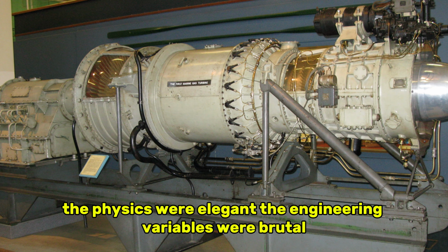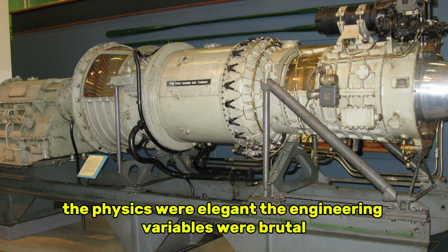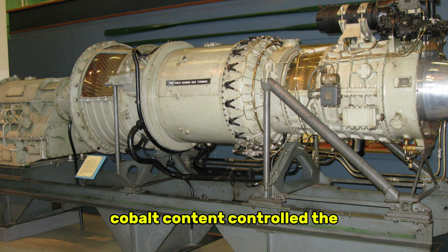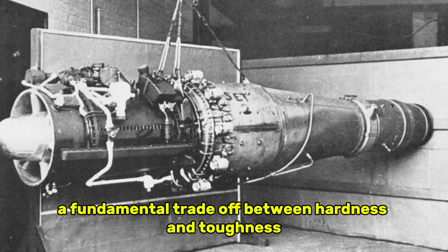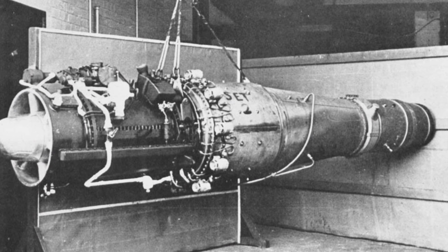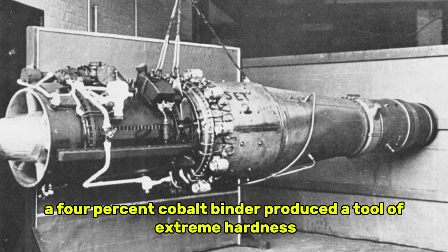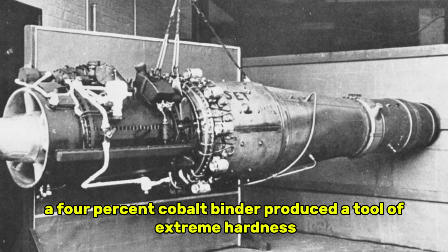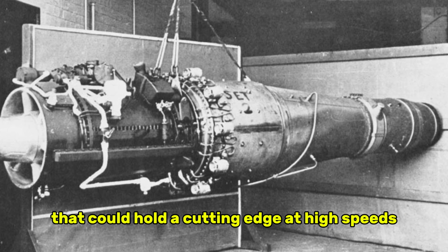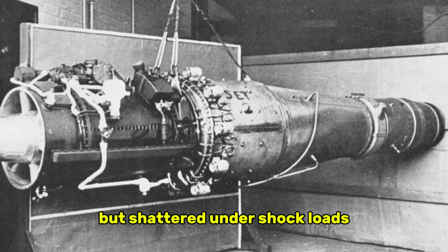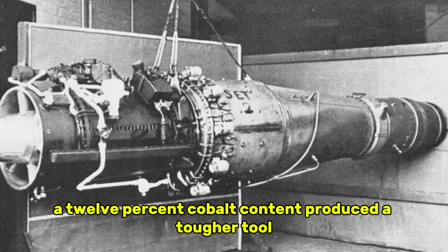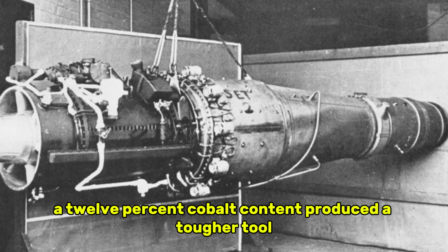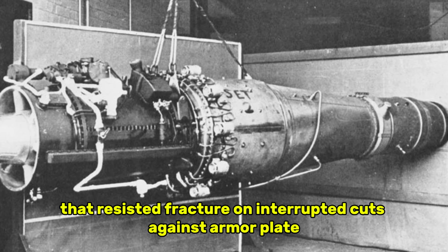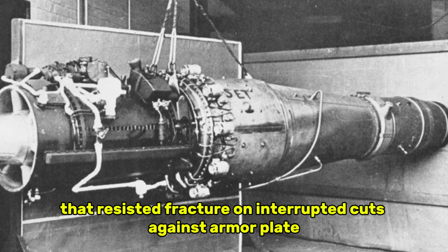The physics were elegant. The engineering variables were brutal. Cobalt content controlled the fundamental trade-off between hardness and toughness. A 4% cobalt binder produced a tool of extreme hardness that could hold a cutting edge at high speeds, but shattered under shock loads. A 12% cobalt content produced a tougher tool that resisted fracture on interrupted cuts against armor plate, but wore faster under sustained high-speed finishing work.